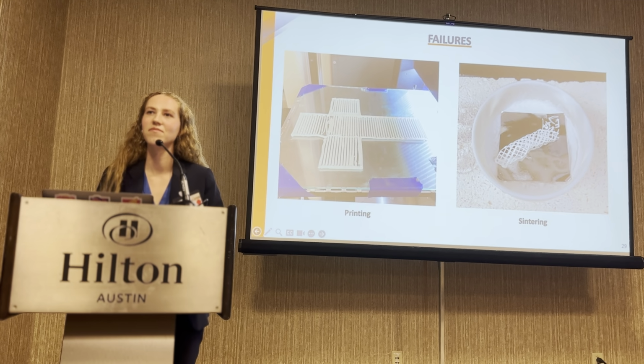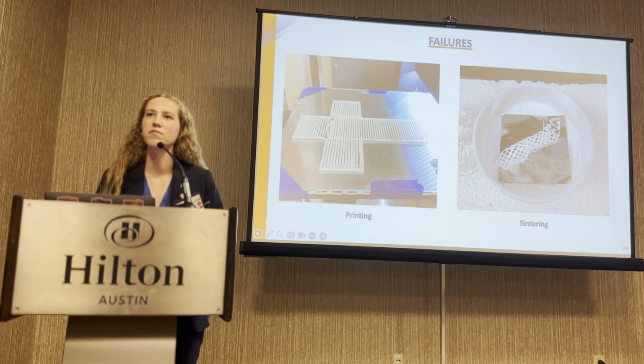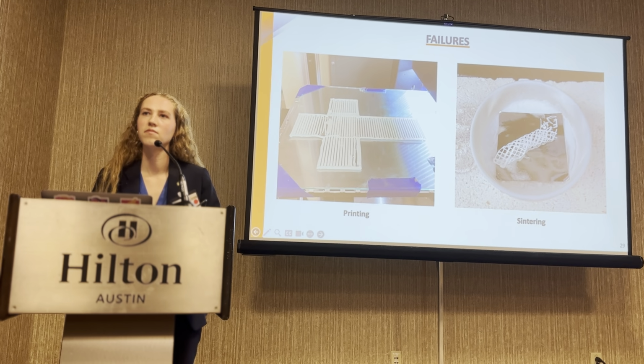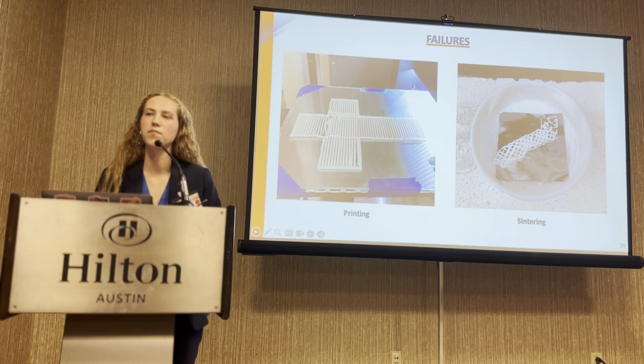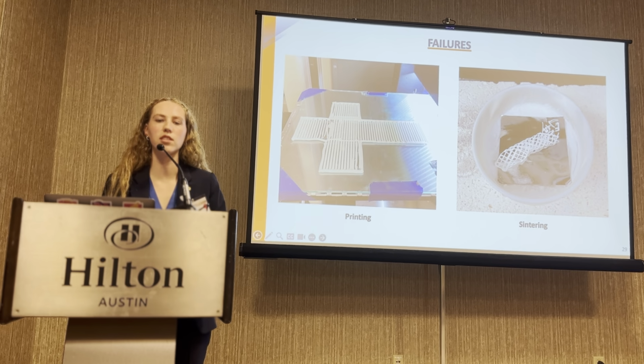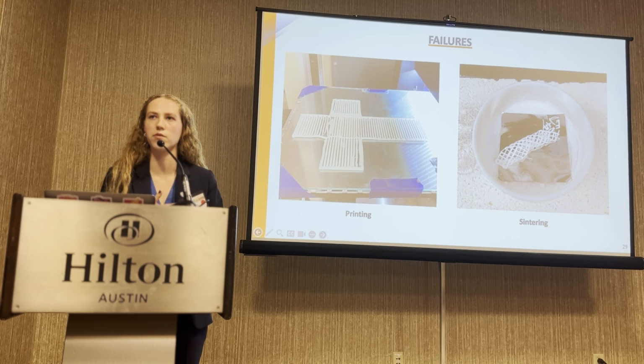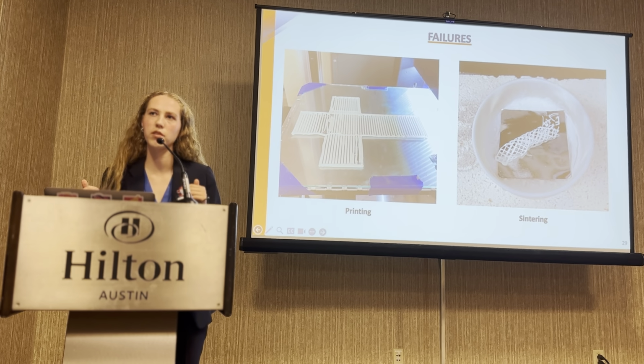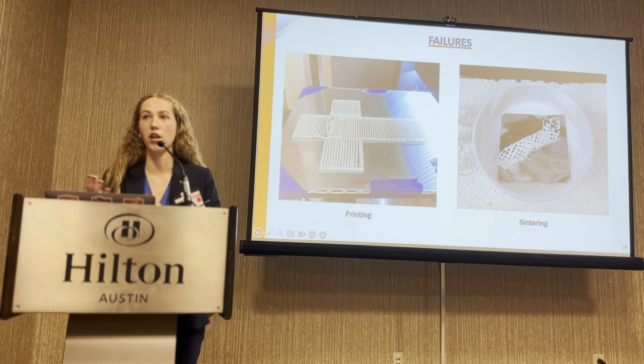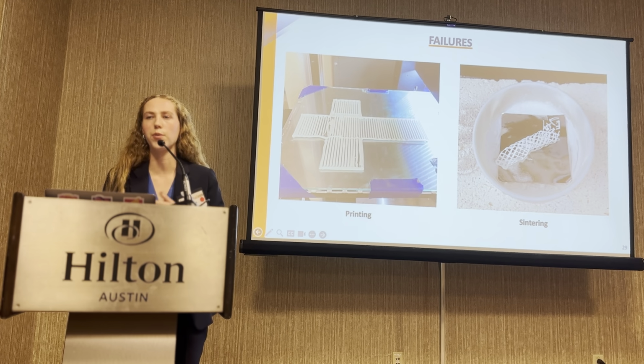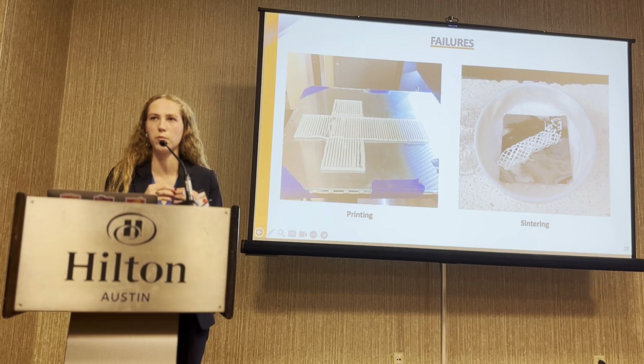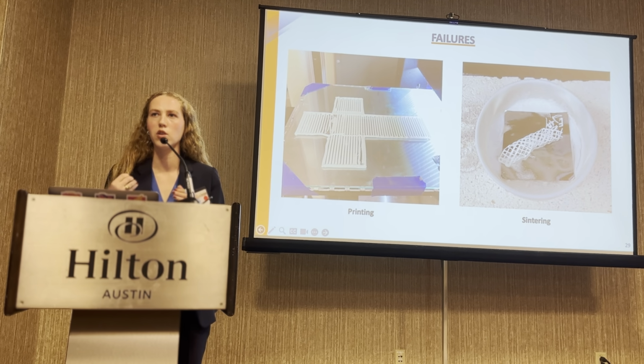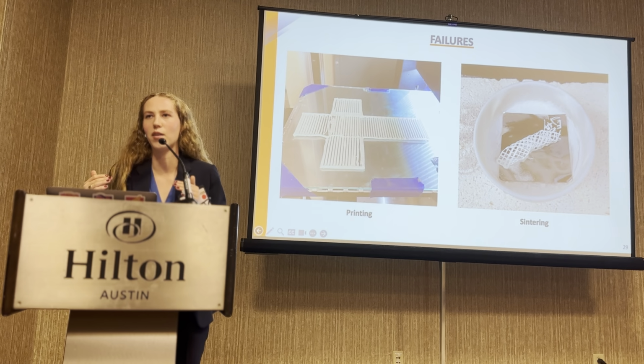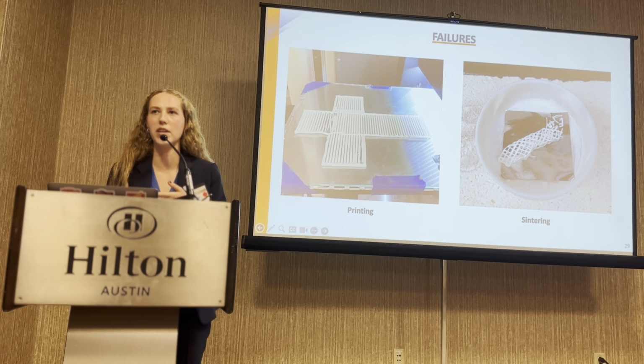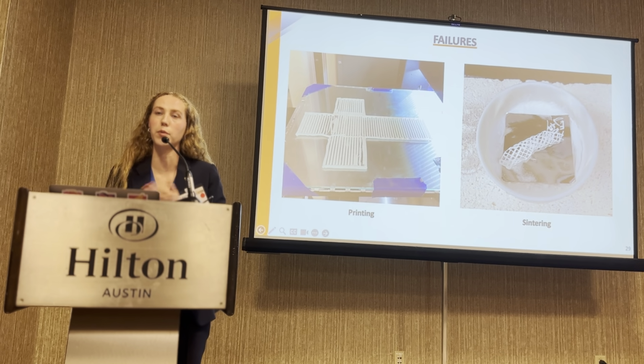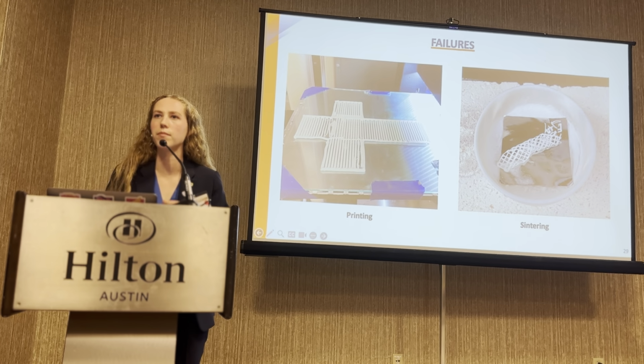You mentioned placing the center of mass at the bottom of the crucible during sintering. Is that because you see some sort of structural collapse during the sintering process? Yeah, so one of our challenges when creating these parts that survive sintering is to balance the components in the ink recipe. When you have a thinner ink, especially an under-processed ink, it's more likely to collapse. And when you haven't let the ink set long enough after printing and forming before sintering, it tends to have more deformation. So we were balancing multiple components of the process, and one of the ways we found to mitigate it, if we had forgotten to let it sit long enough or had under-processed the ink, was to sinter it with the center of mass lower.